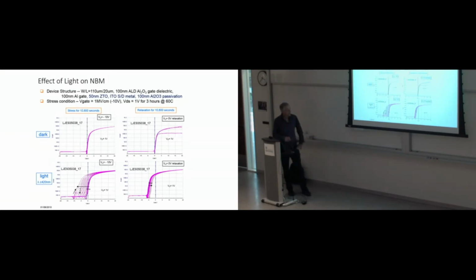But people understand that, and so they have been able to deal with it. That's why metal oxide transistors can be used for drive electronics, although I guess people are going to laser annealed poly as the preferred thing, but you can make things that are fast enough for at least driving the gate drivers and bigger displays. With bigger displays, the pixel time starts becoming faster than amorphous can handle. So if you have a 4K display that's 80 inches, for the time scale for switching that, there's too much capacitance, so you start needing metal oxide for the active matrix.